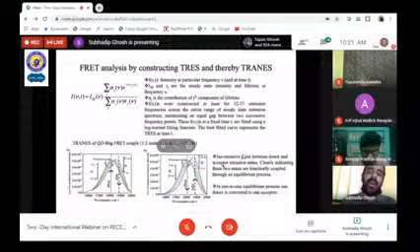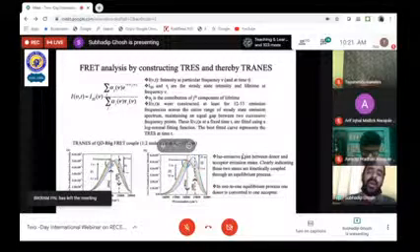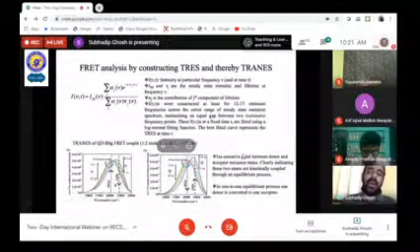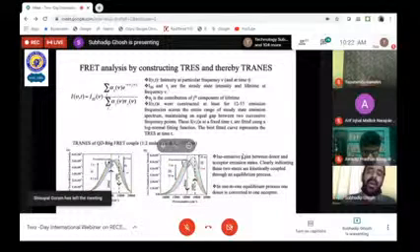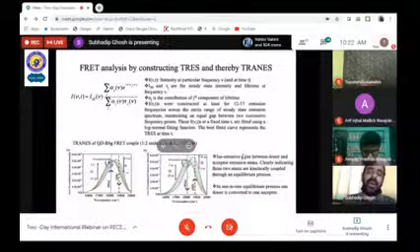Now we found that as time progresses, the emission intensity of the quantum dot decreases, and at the same time the emission intensity of the rhodamine 6G portion increases. And again we found, like in steady state, in the time-resolved study also there is an isoemissive point, and this indicates that FRET is going on. Now the question is, since the donor emission and the acceptor emission are so closely spaced, how would one study the quenching process?